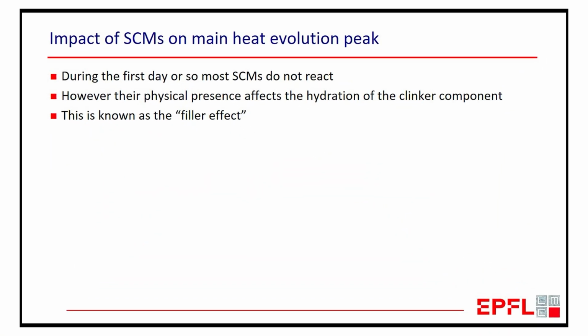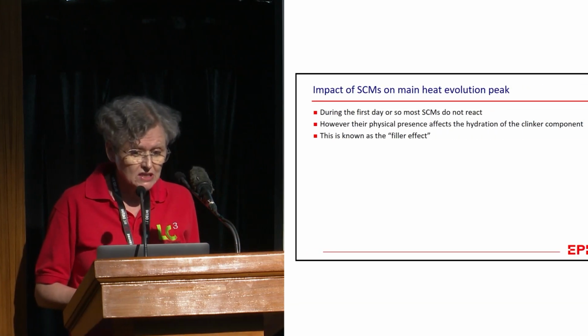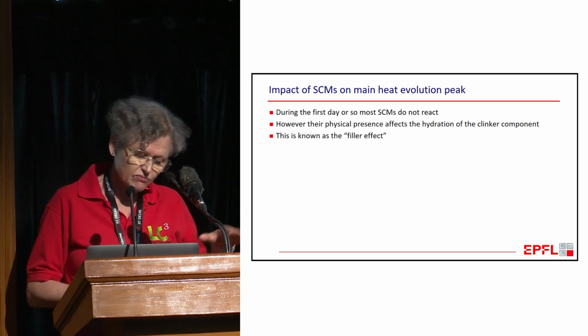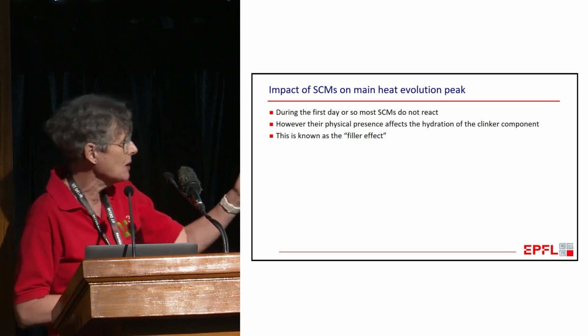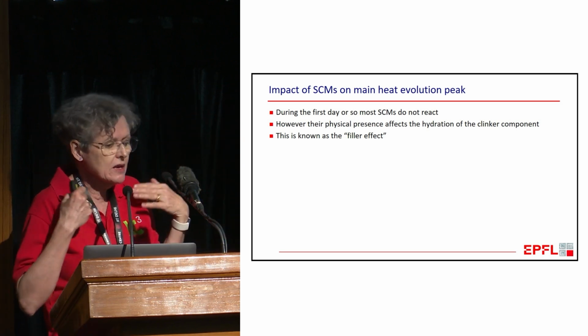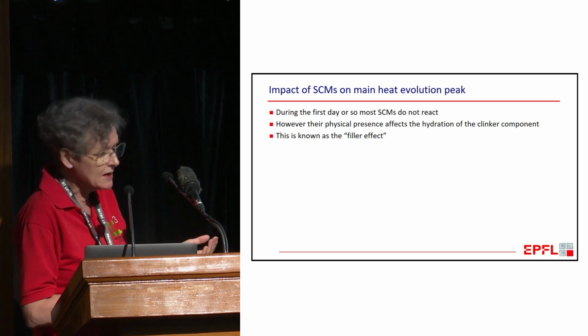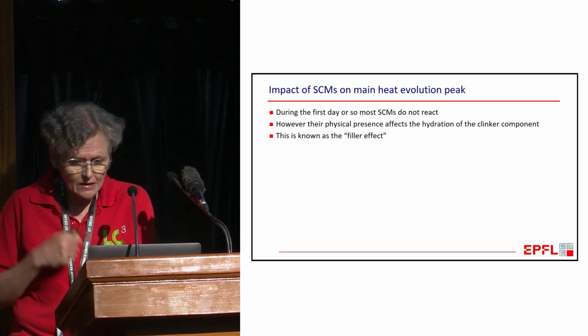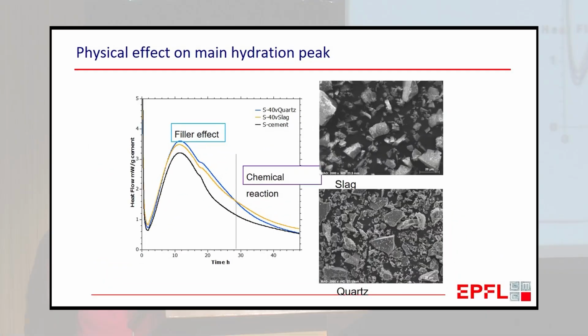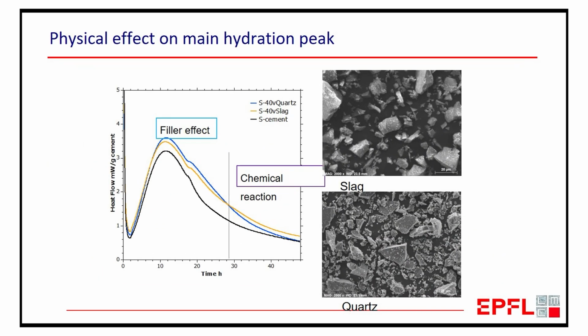but I'm just going to talk about the filler effect here and understanding that filler effect, because it's quite important, because during the first day or so, most SCMs do not react. Calcined clay actually reacts a little bit, but it's still the basic clinker, the Portland cement part, that dominates the reaction. And even then, the SCMs have an effect on that clinker reaction.